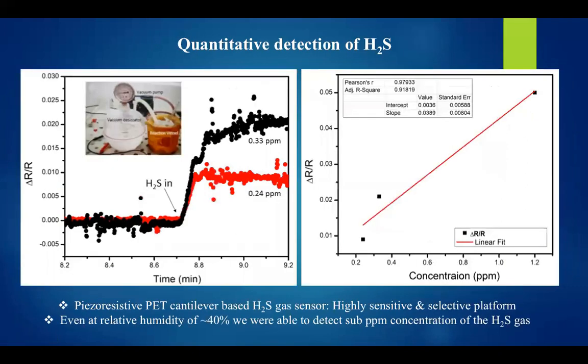To find out the limit of detection of these cantilevers, we did quantitative measurements in a home built setup where we generated H2S in a reaction vessel, and a known amount of H2S was allowed to get exposed on the cantilever sensors. The cantilever sensors were separately used for each concentration, and because the selective material is reacting with H2S, we can see that there is a linear dependence of the delta R on the concentration of H2S. We can say that this particular material and the piezoresistive PET cantilever described here is quite sensitive to H2S.